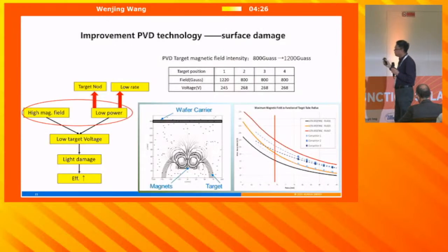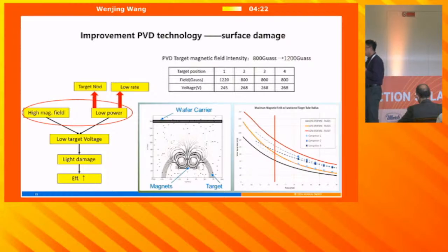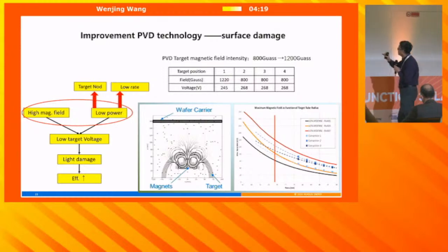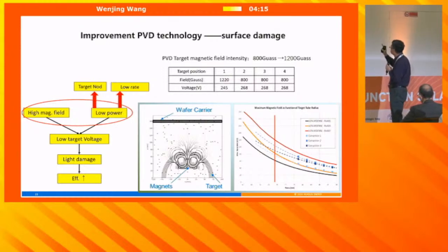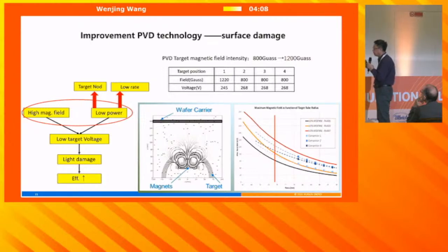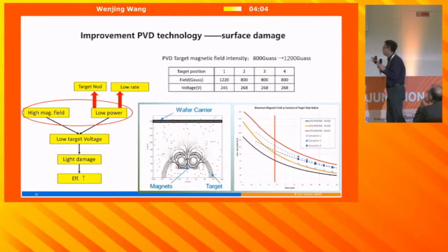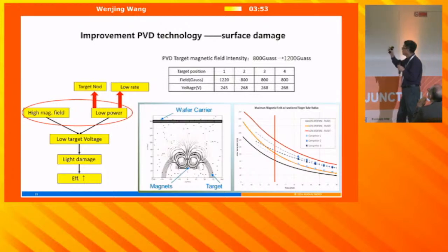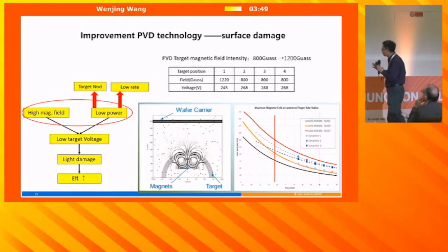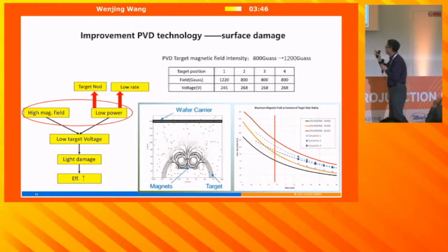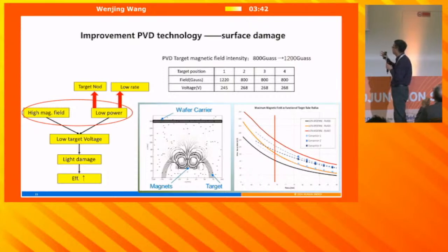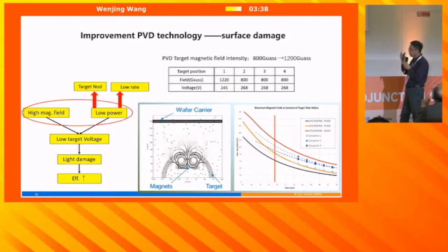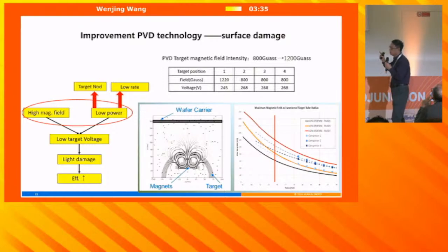And also for PVD, you have to avoid damage to the surface. So we have to increase the target field, which reduces the target voltage. If the target voltage decreases, that decreases the surface damage, so the efficiency will increase. The other method to reduce the damage is to use low power. But if you use low power, the deposition rate will decrease, and there is also the phenomenon of target nodules. So that's a problem. So right now the trend is to use a high magnetic field target.